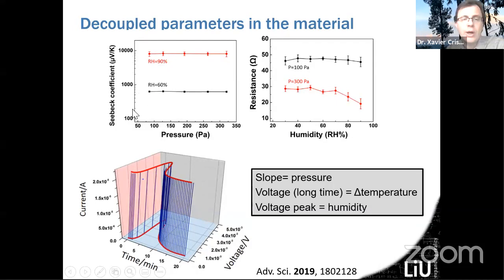For instance, look at the Seebeck coefficient at different humidity levels. When I apply a pressure, it's constant. Look at the resistance here versus humidity for different pressure, it's almost constant. So there is a window of pressure, humidity, and temperature gradient where we can read each parameter independently, with no cross-talking. We completely disconnect the talking between those values by an intelligent design material—one material that can read three parameters independently.